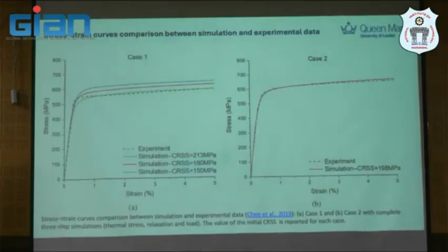Because they want to validate this with the critical resolved shear stress, they first simulated an experiment, to calibrate the model: what is the critical resolved shear stress here? So you will see the modeling and experiment match quite perfectly, not just well, it's very perfect.